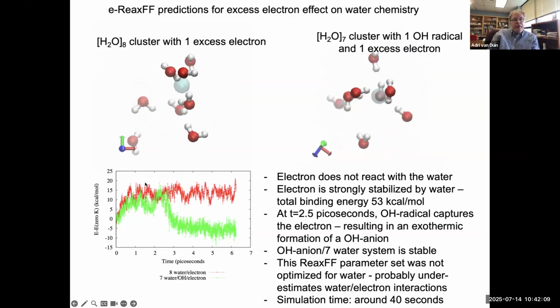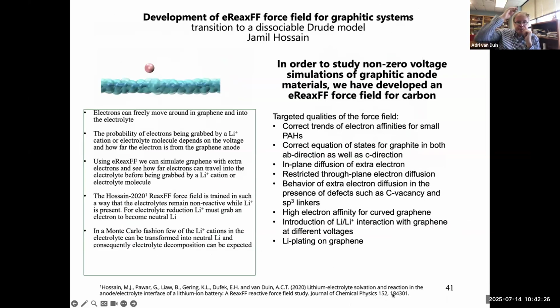If we are, however, at an OH radical, so now I remove the hydrogen, you see after a while the electron finds the OH radical and turns it into an OH anion. And we see indeed energy release. These simulations are very fast, so doing this with DFT is very expensive because you have to do time-dependent DFT, and it typically can take you several weeks to do this type of simulation. This simulation in ReaxFF only takes about 40 seconds.